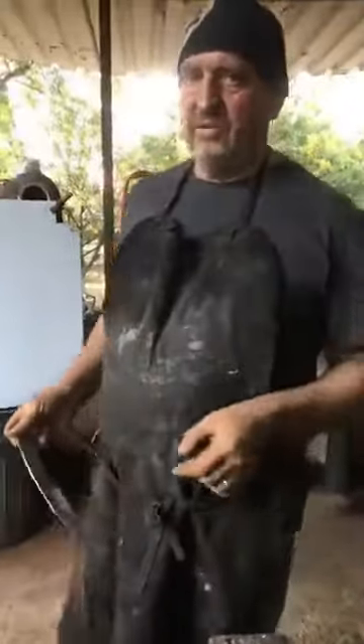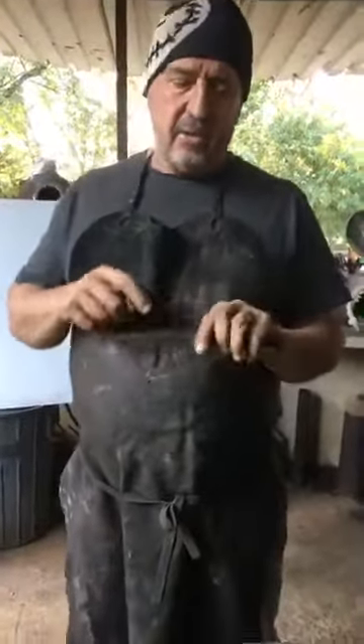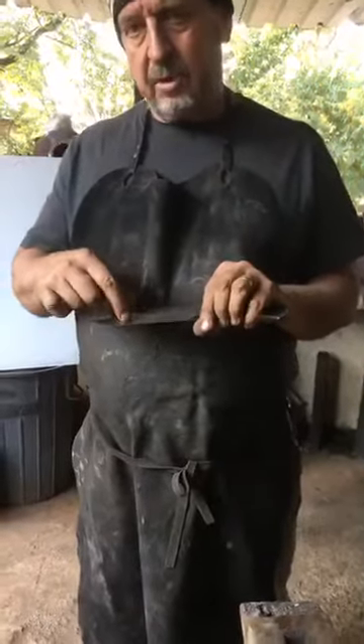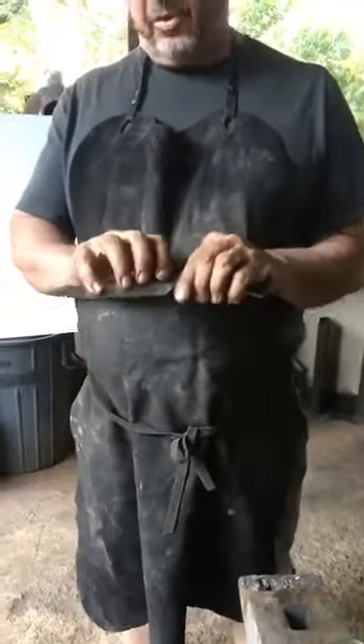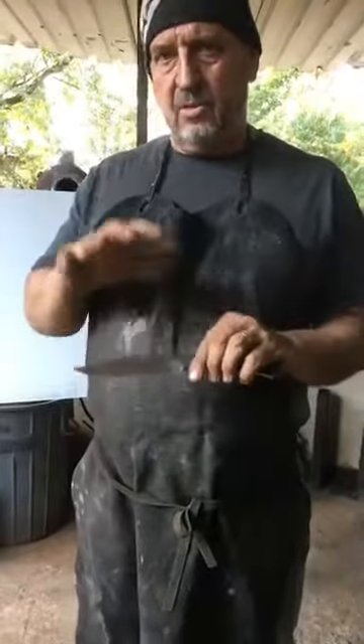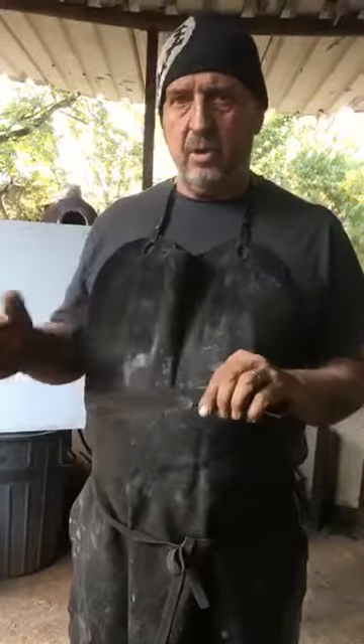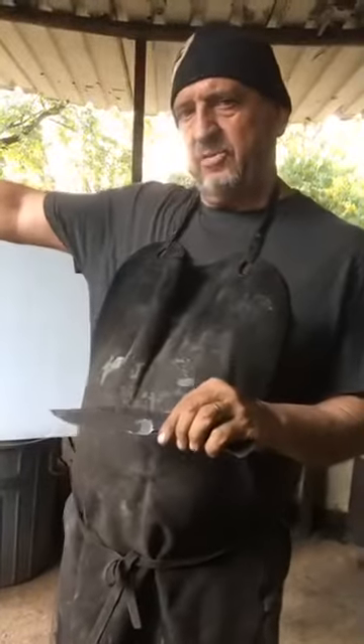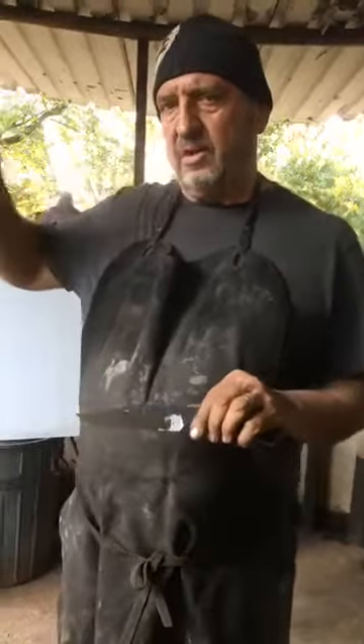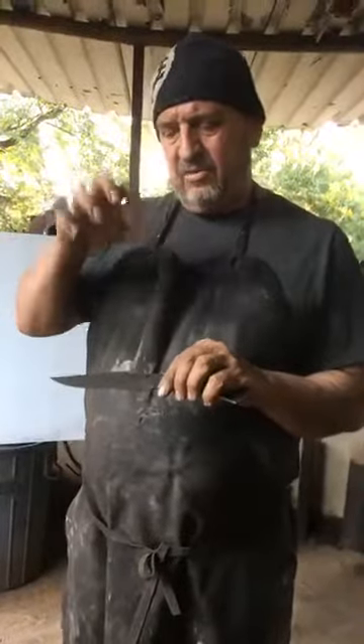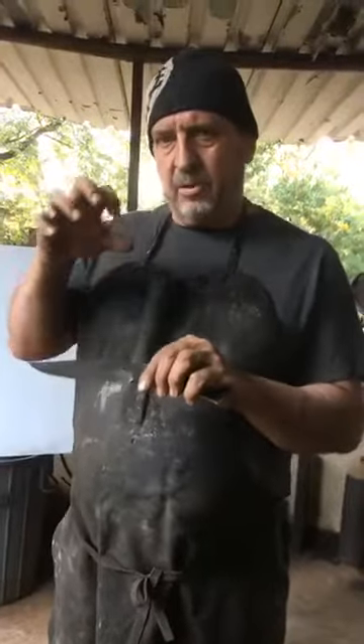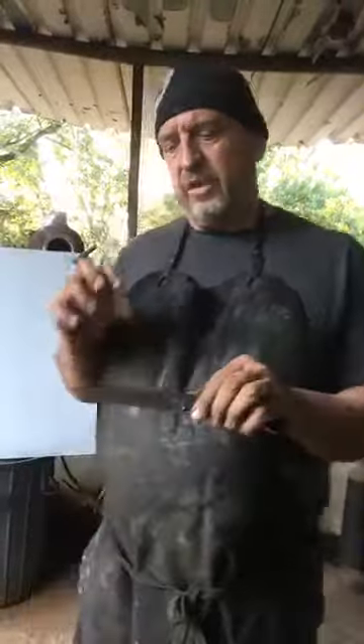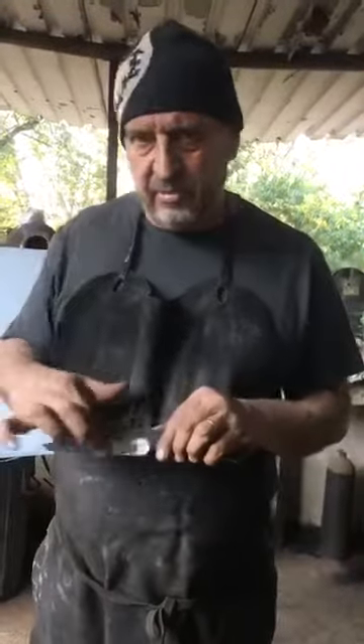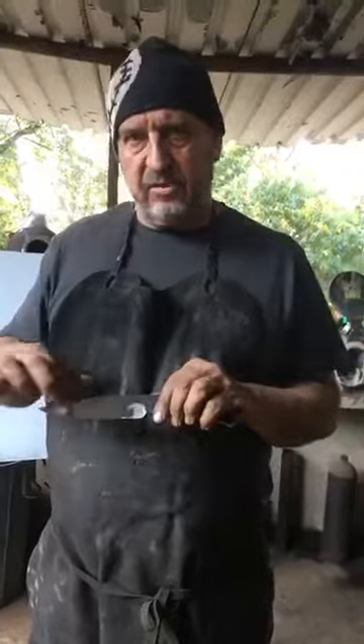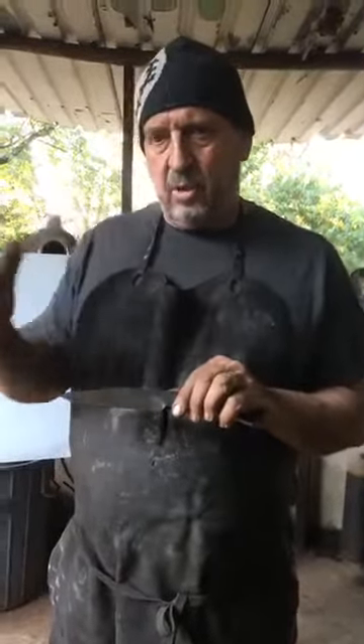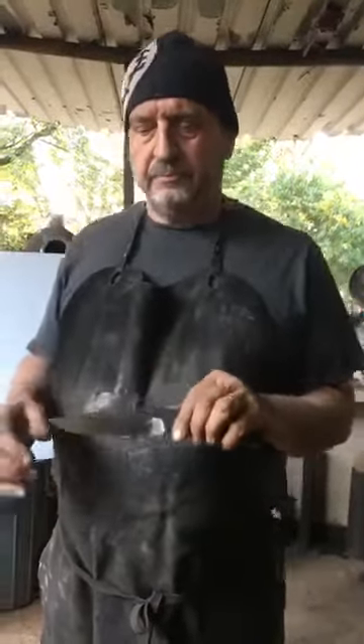The Japanese found this out and have perfected it by putting clay on the back of their blades. The clay gives it a thermal blanket that heats it up to what is called critical nowadays. In the old days, you used to chase all the apprentices out of the workshop because nobody was allowed to know that key secret temperature as to when the blade was hot enough to quench it, so that it would form martensite on the edge. Martensite is the key crystalline structure we are after with the plain carbon steel.